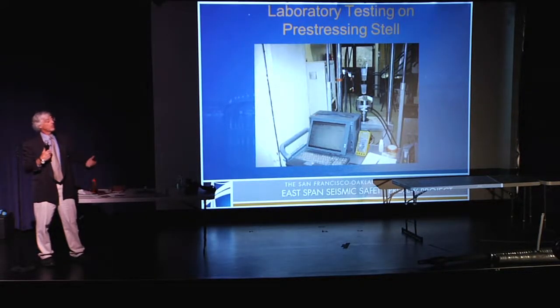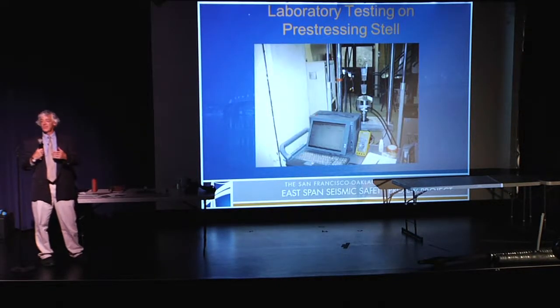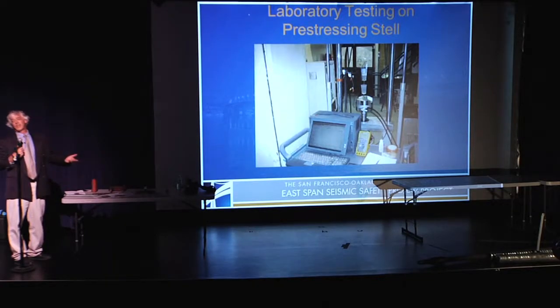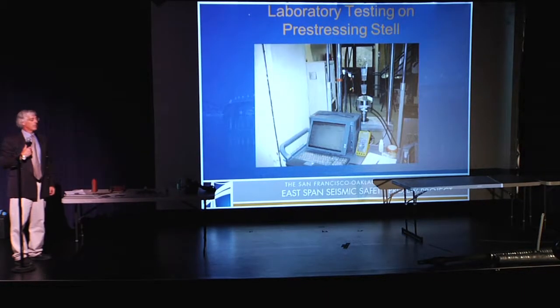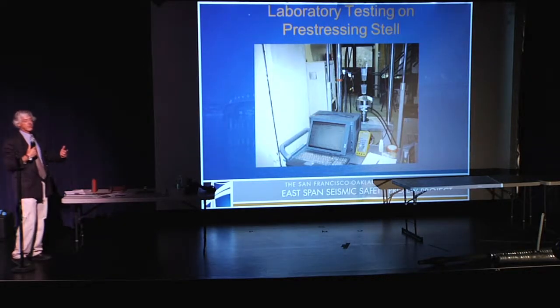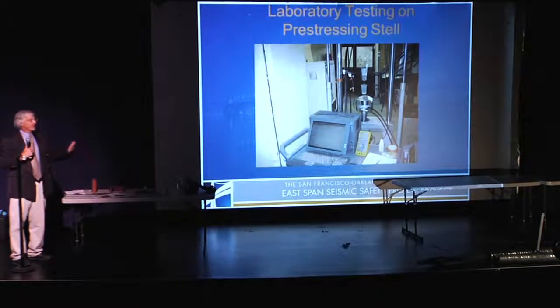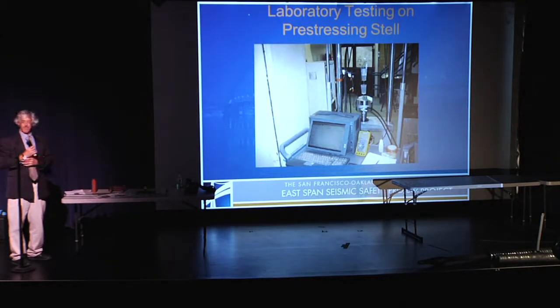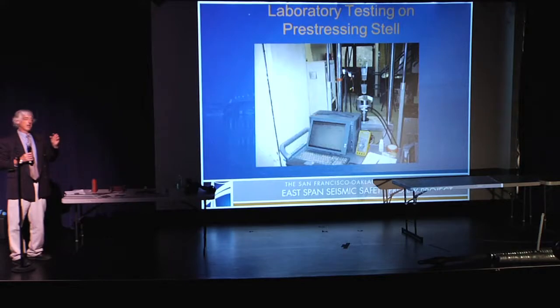So we had a lot of information, thousands of photographs. I lost count of how many videos we took, and then we actually removed some, did some testing. Our corrosion expert, Rob Reese, actually opened one up as a high school student would open up and dissect a worm. We also involved FHWA and their corrosion experts on the East Coast. We actually also had the external independent peer review panel with Joe Nicoletti looking over our shoulders on this. And at the end, what we had was statistical information, strong engineering information, that something like 1.5% of the strands had what we termed moderate corrosion. That means we were losing about 5%, something like that, of their strength. Didn't mean it went away, just means it was reduced to a certain degree. But still, the overwhelming amount of the steel was still meeting the full ASTM tensile loads.